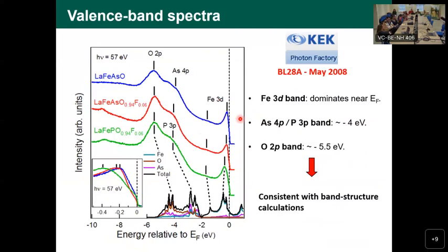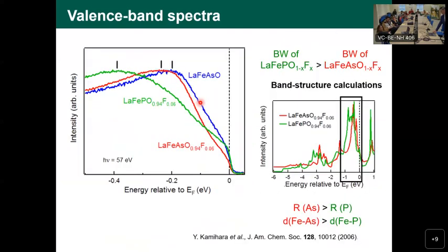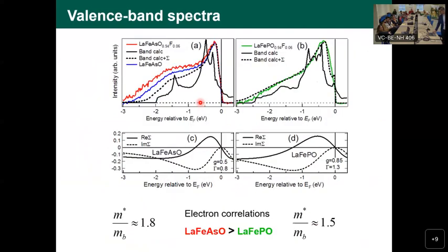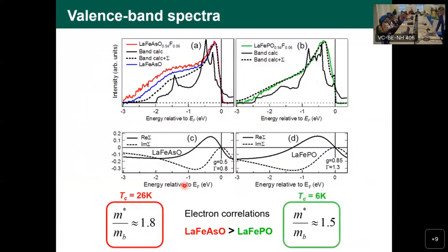That's okay. However, that's very strange because iron is magnetic, and magnetic materials actually are the enemies of superconductivity. They tend to kill superconductivity. However, this magic recipe, sometimes we call it, of iron and arsenic, and this structure actually made iron play a constructive role in the phenomenon of superconductivity. That was our first report, and of course, we did some detailed study about the bandwidth and so on. And here, interestingly, we noticed that the degree of electron correlation, so how much these electrons interact with each other, represented by this factor here, 1.8, was larger for higher Tc. So that was important information at that stage.